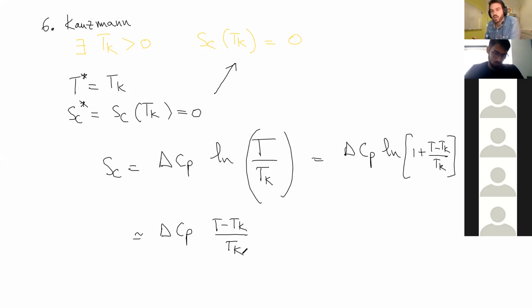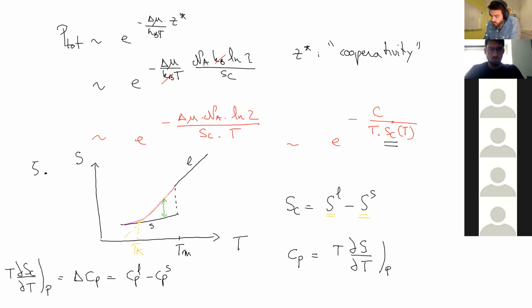Okay, you see where I'm going now. It seems that the configurational entropy is vanishing linearly with temperature near the critical point. Remember, we were saying that the typical probability for the system to relax goes like 1 over temperature, but this is not changing much compared to the configurational entropy. So there should be a vanishing of the probability and an explosion of the relaxation times that looks like the VFT law.